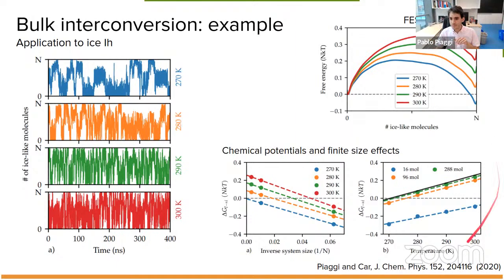Okay. We can also plot this difference in free energy or chemical potential as a function of temperature for the different system sizes. And we see how the coexistence temperature is shifted for different system sizes, a very clear sign of the finite size effects. And in black, I'm showing the extrapolation to the thermodynamic limit. Okay, so this is one of the methods that I'm proposing to work on in the tutorials.